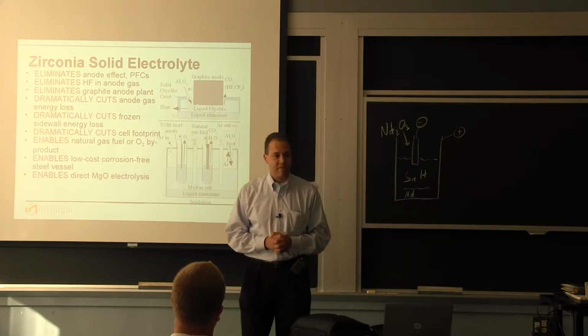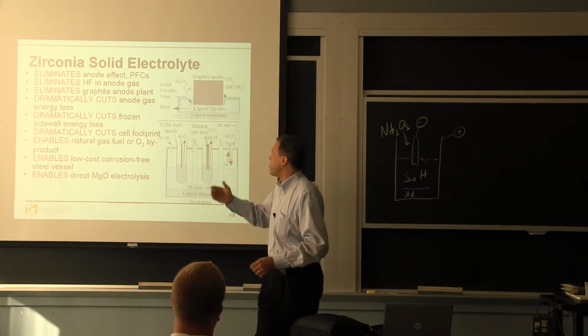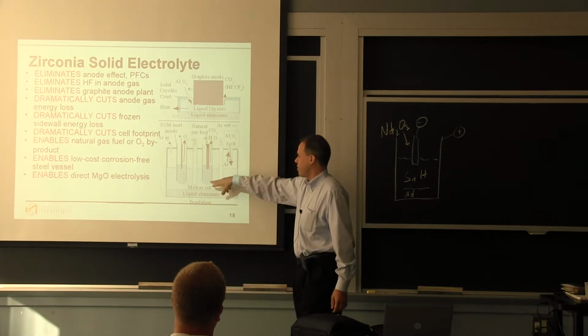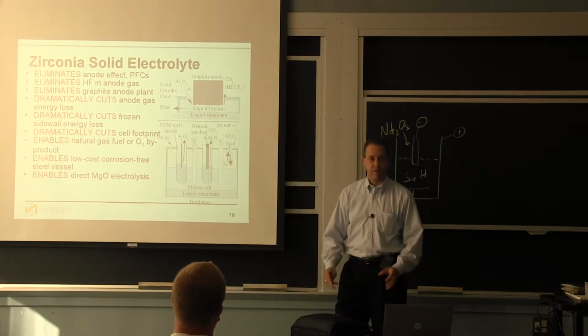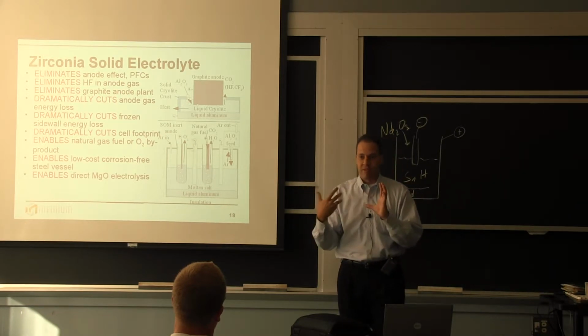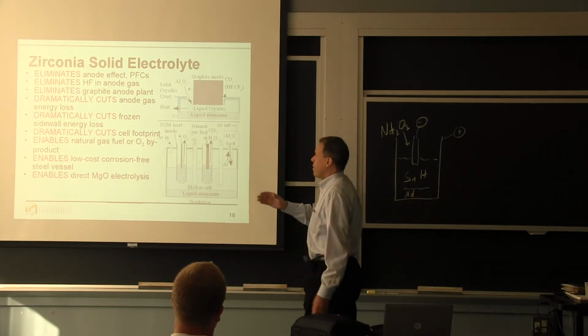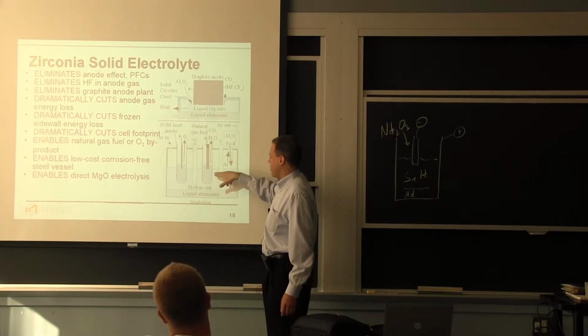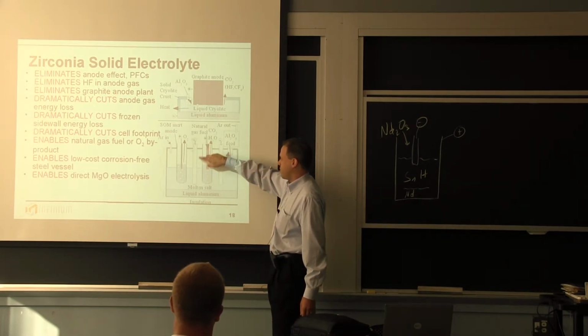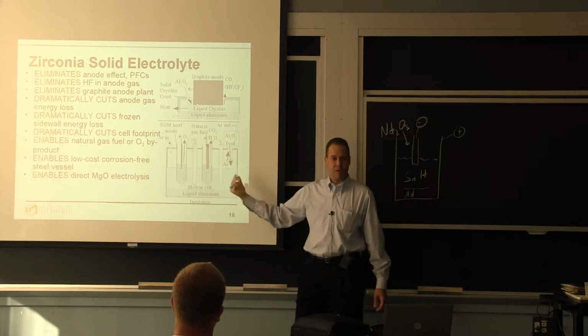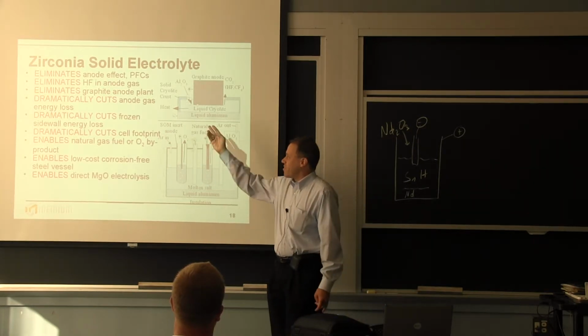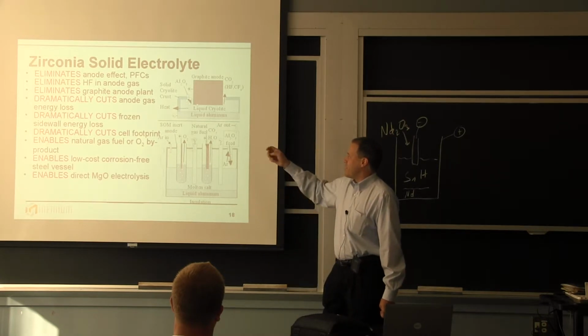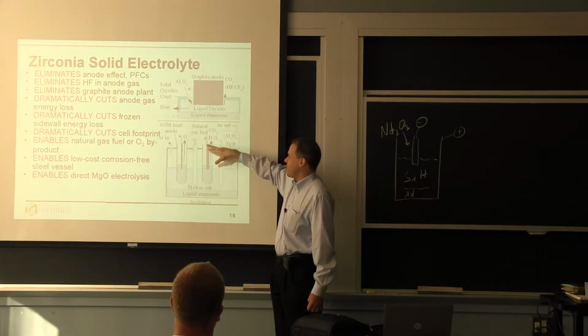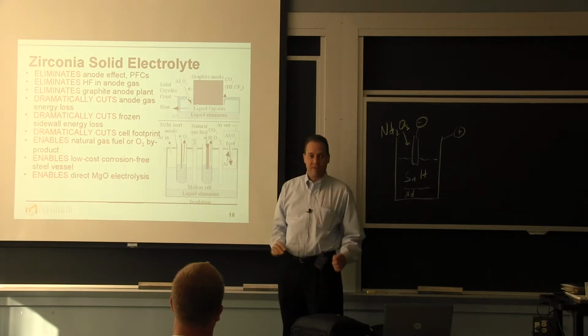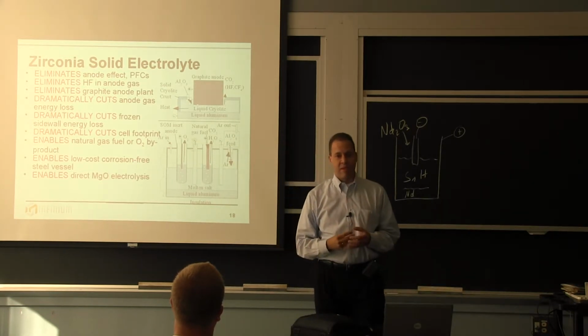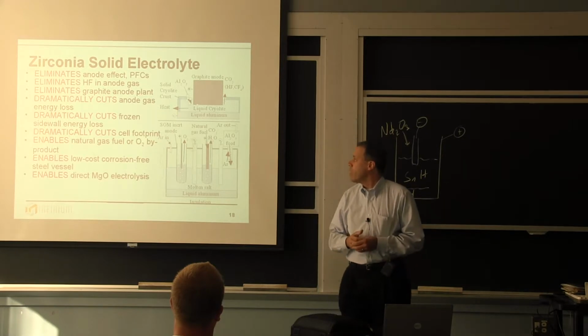C2F6 is about 9,000 times the global warming potential. So this eliminates that because you don't have any fluorine in contact with the anode. The zirconia is very selective. It only allows oxygen through. So it eliminates HF in the anode gas because the anode is in a separate chamber from the rest of this. It eliminates the graphite anode plant. As I mentioned a moment ago, you can capture the energy from this CO2 and water, or from this oxygen, where you really can't from the anode gas in a Hall cell plant because of the HF.